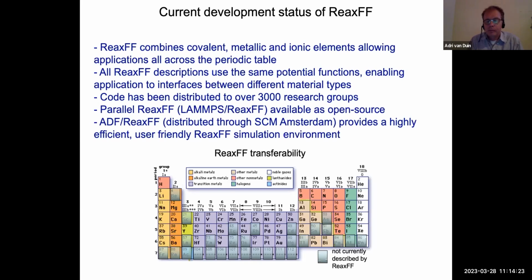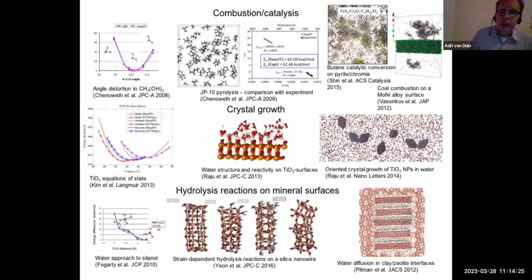So just a couple of examples of ReaxFF use to give you some idea how these projects typically get formulated. With ReaxFF, one of the early applications was in combustion, here on the top. We train ReaxFF, for example, against all possible valence angles, angular combinations related to hydrocarbon combustion. So for every combination of oxygen, carbon, and oxygen, we make a small molecule that has that angle in it. And at the DFT level, we then scan that bond, scan that angle, and train ReaxFF against it. It's clearly non-reactive, but that's part of our training set.